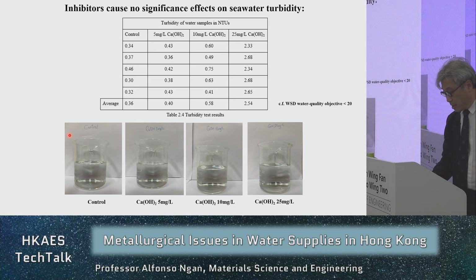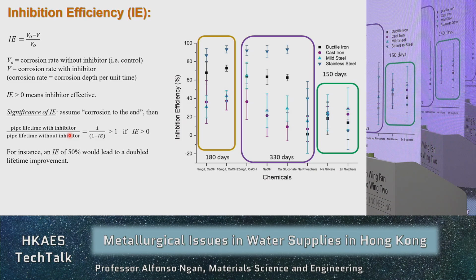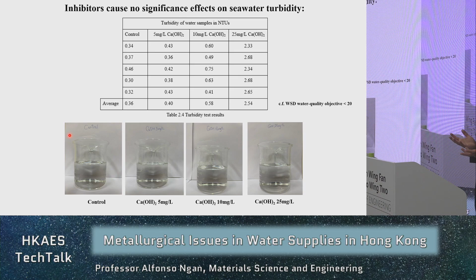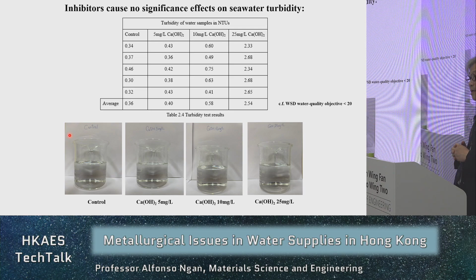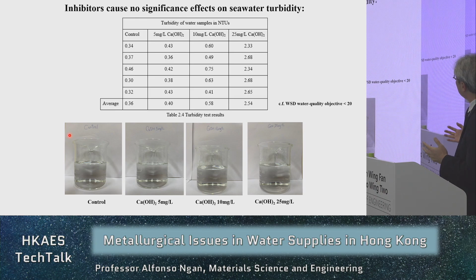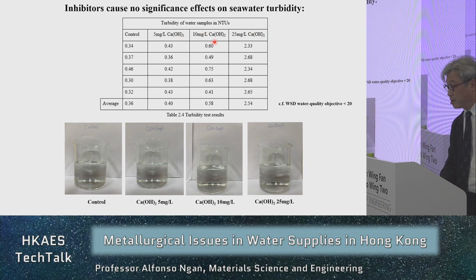Okay, so basically our full-scale test, not full-scale, but the plant test shows that in a lot of the chemical inhibitors, the effect is not good, not bad, it's quite good. But of course, another concern is the turbidity. I mean, after adding the inhibitor, would it deteriorate the turbidity? The answer sometimes is yes, but for this group of inhibitors, the calcium hydroxide, in fact, the change is very, very small.